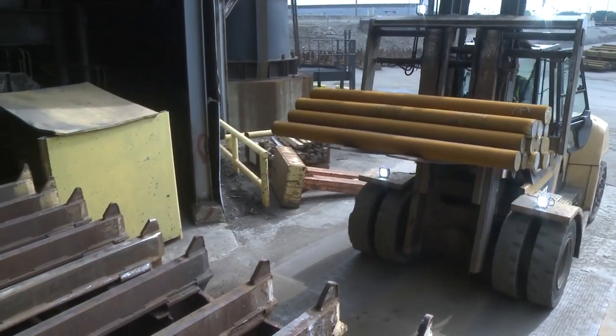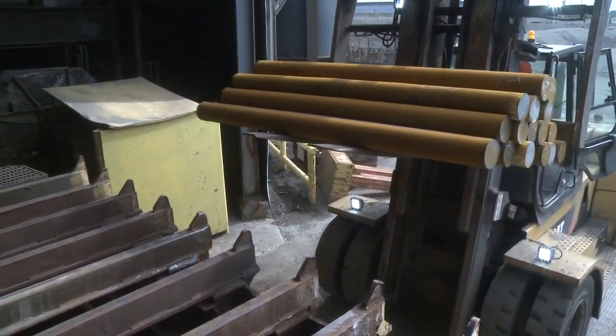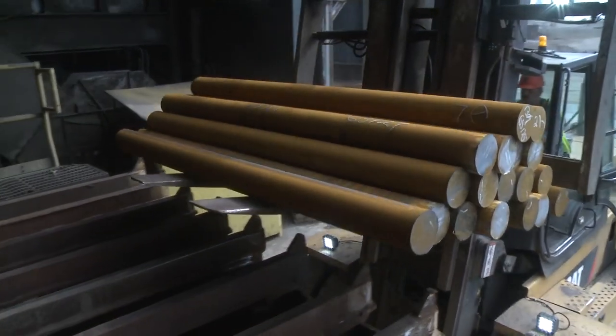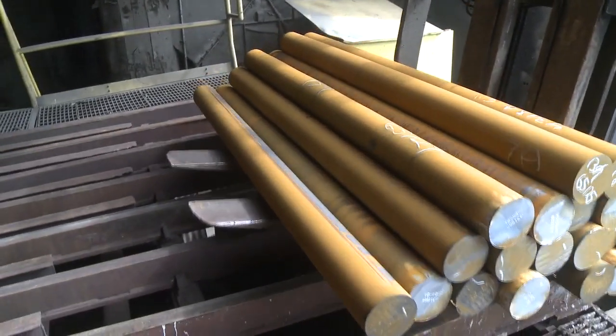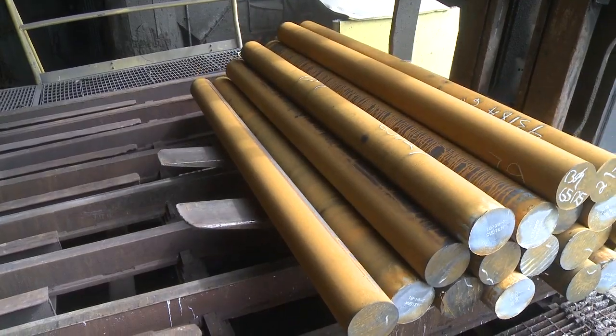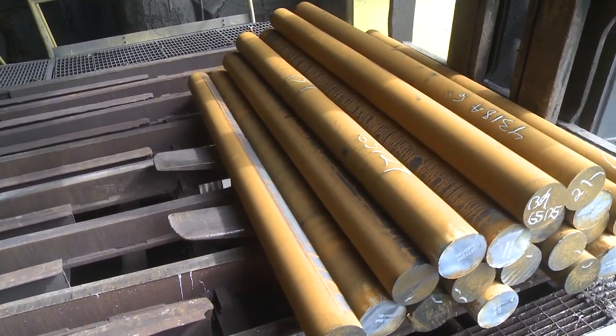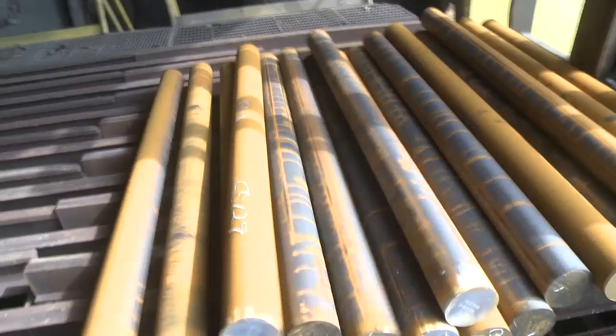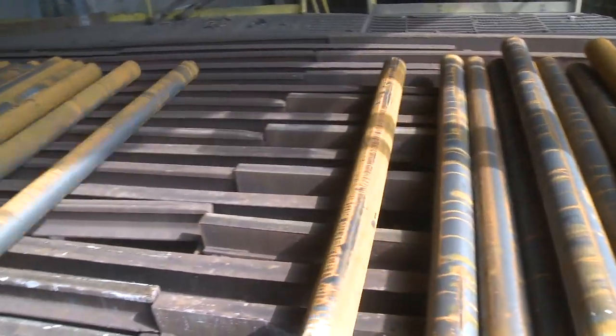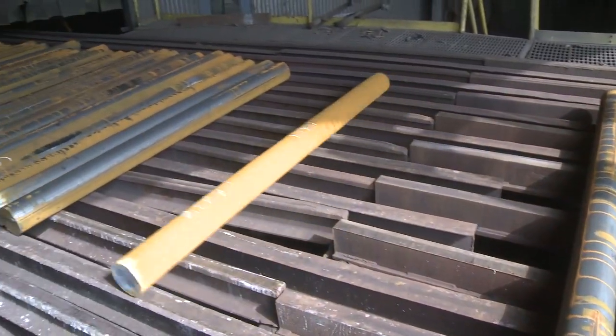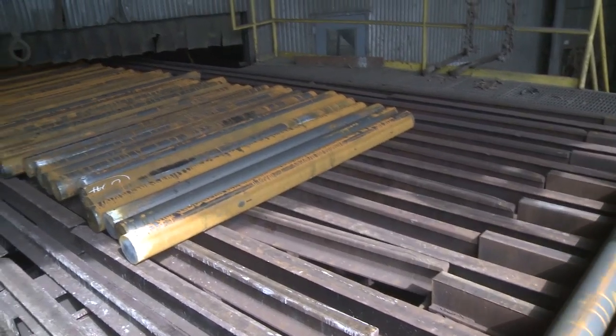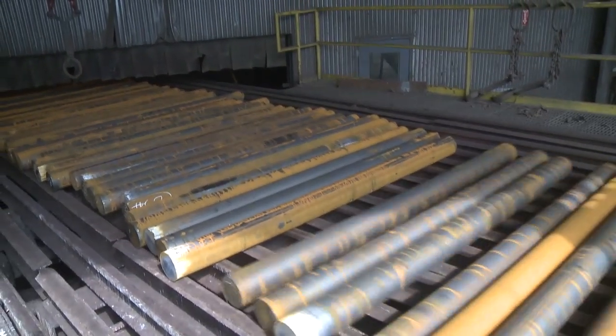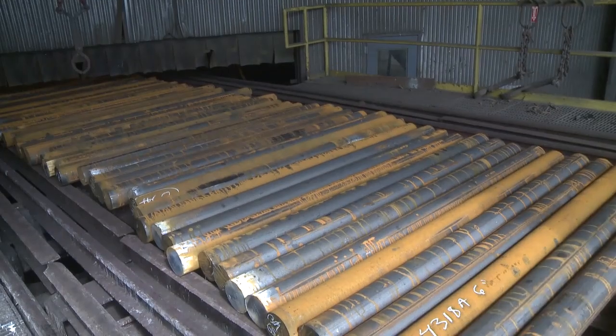At the charging table, we receive billets, or round pieces of steel, from the nearby Faircrest or Harrison plants. Here, we carefully count and mark check the billets to make sure they have the correct heat number, outer diameter, and length for the order. Prior to loading, we also review the billets for any defects. We then convey the billets to a star wheel that positions each billet for insertion into a rotary hearth furnace for reheating.